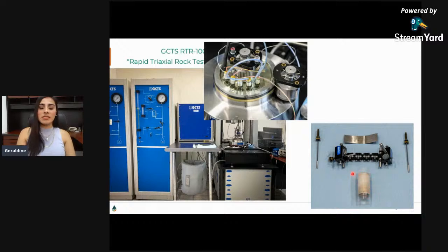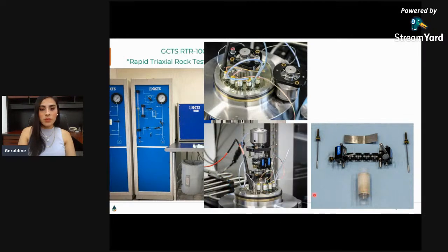Normally, you put the sample inside a sleeve. This is to protect the sample from the oil that will be applied around it in order to apply a confining pressure. Then this picture shows how the sample looks already assembled. Here you can see the bottom platen, top platen, the LVDTs on both sides, and the radial LVDT around the sample. Then this assembly is put below the cell. The cell is lowered and filled with oil. Well, this is in case you will do a triaxial test. If you will do a UCS, it's not necessary to fill with oil.